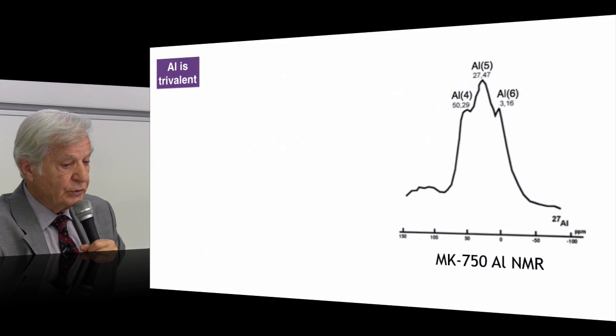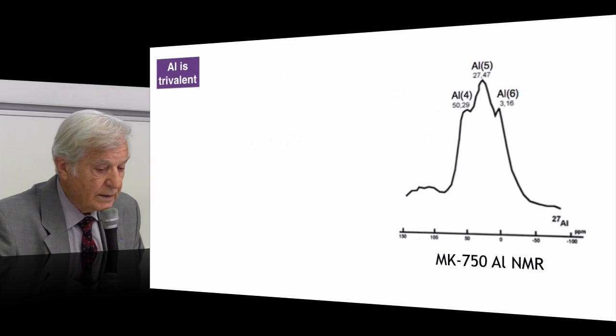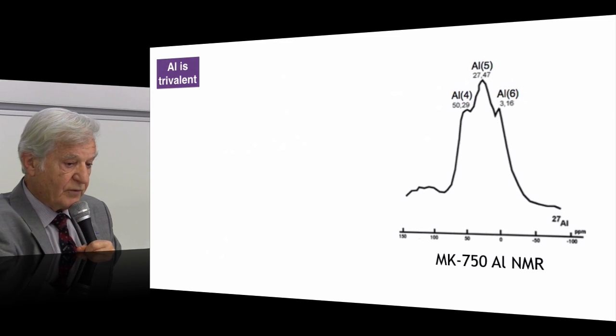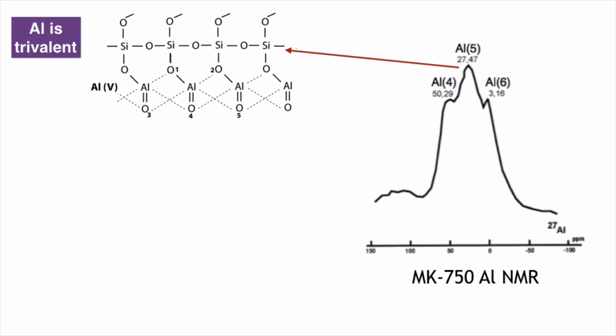And if you look back to the Metakaolin nuclear magnetic resonance for aluminum, then what you find is Al5 has this chemical molecular structure which shows the reactive sites, aluminol. And you see here the aluminum is coordinated physically close to 1 oxygen, 2 oxygen, 3 oxygen, 4 oxygen, 5 oxygen. That is, it is penta-coordinating, but it is a physical, a geometrical behavior parameter. It is not a chemical parameter. It doesn't give any information about the reactivity of the system.